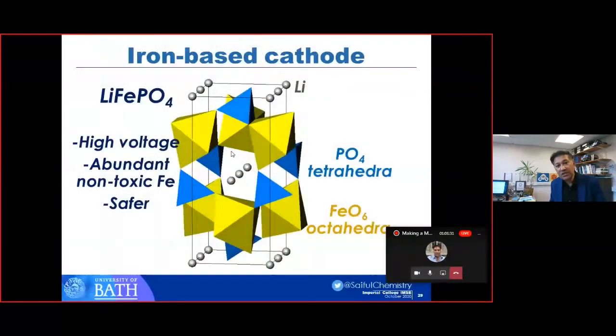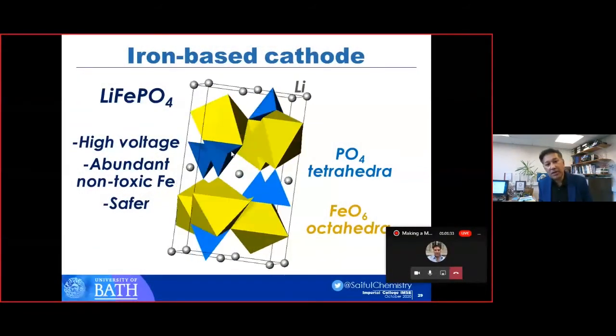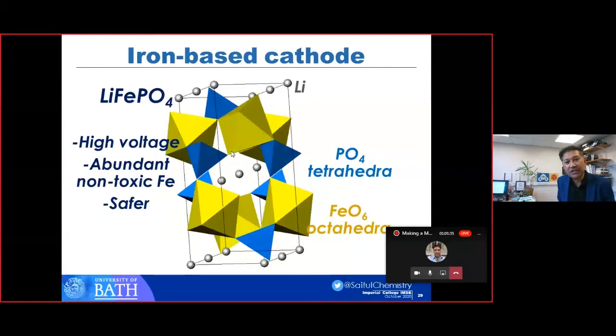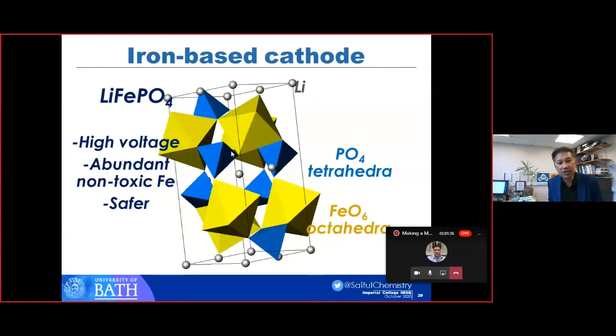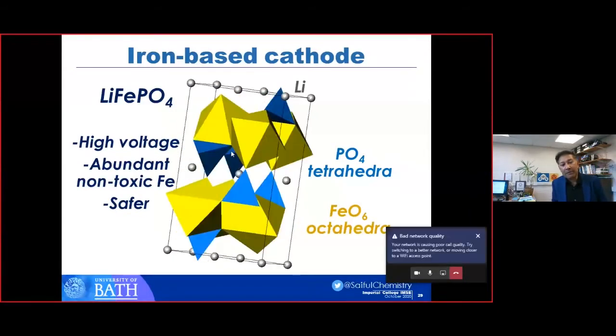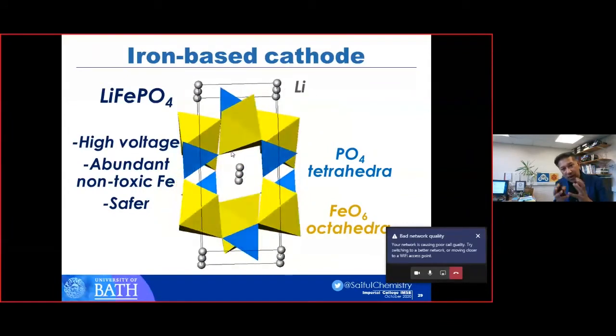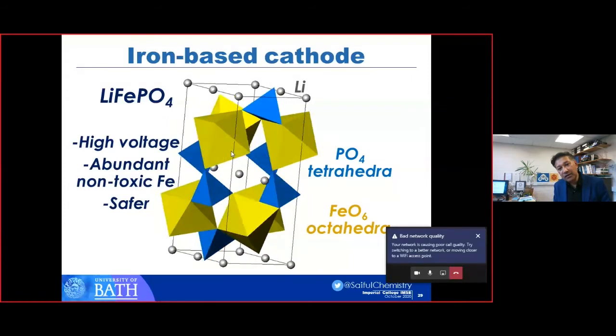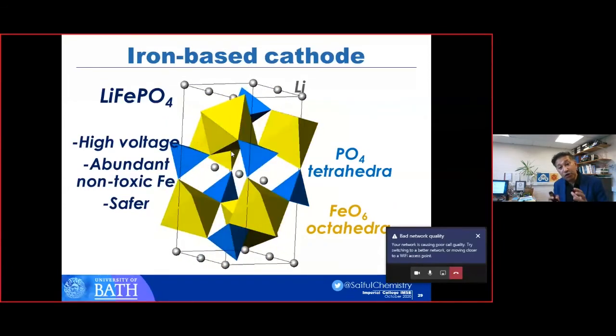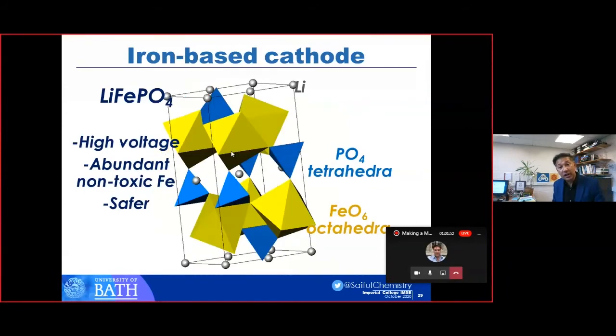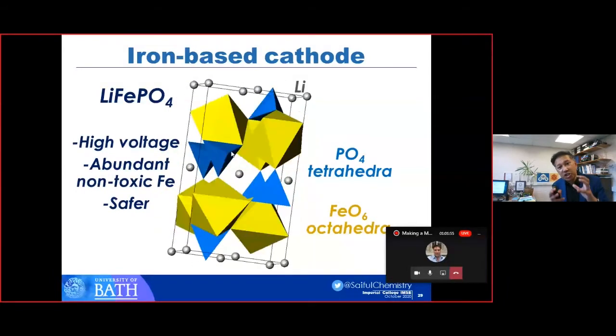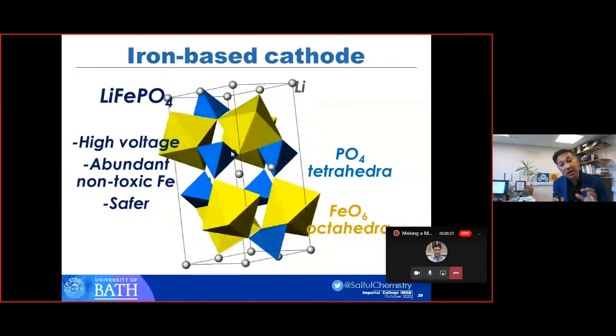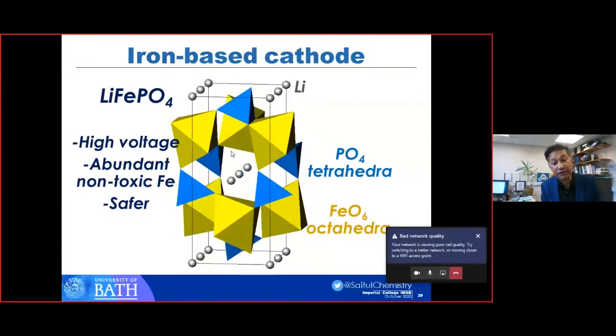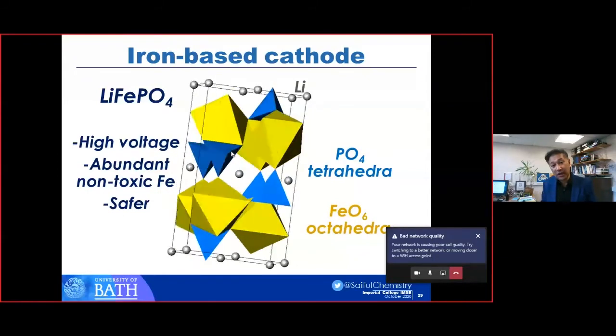But what about new materials? So this is probably the most studied cathode material in the last 15 years, lithium iron phosphate. The structure I'm rotating here is made up of these iron octahedra in blue and the phosphate tetrahedra in yellow, and the lithium ions are in grey. And you can see straight away, even if you're not a structural chemist, the structure is very, very different to the lithium cobalt oxide.